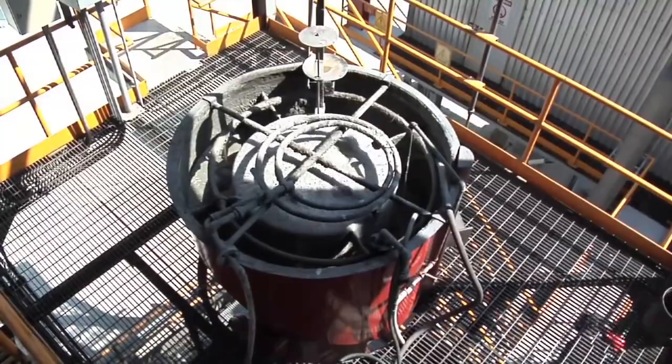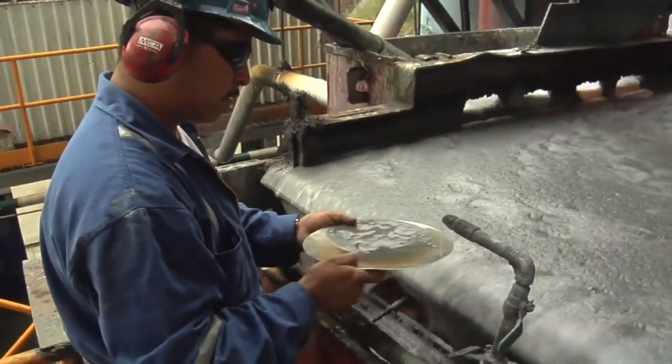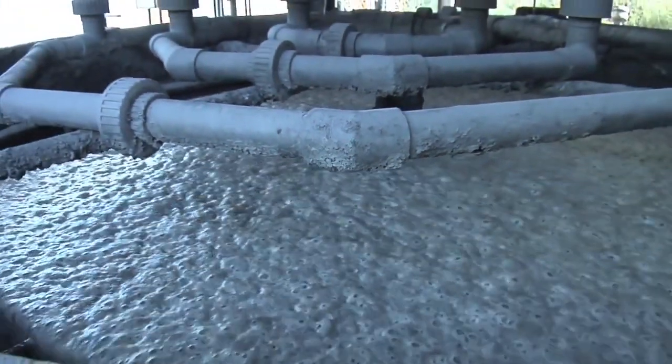After the ball mills, we'll take it from three-eighths down to a fine powder like talcum powder or flour. Separation is done in a few ways. Flotation is a process in which the particles are mixed in water with air bubbles. We add a certain chemical at very low concentrations that attaches to the silver particles and makes them hydrophobic — meaning they don't like water. We're adding chemicals that help material that is normally heavy, such as pyrite, gold, and silver, to actually float, by creating an oily surface on those silver particles. The tiny air bubbles cling to the oily surface and raft the particles up to the top of a tank, where they overflow — kind of like the top of a beer onto the countertop. We suck the water out as much as possible, dry it, and that comes out as a concentrate.